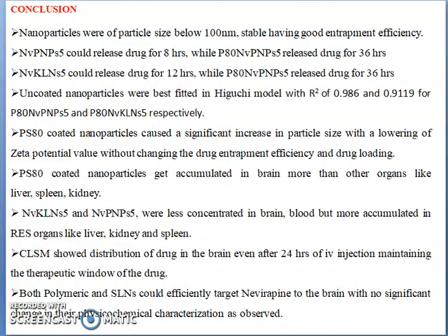So what we can conclude from here is that nanoparticles are very significant in delivering the drug to the brain when surface modified. In our case, polysorbate 80 is used as the surface modification technique. It also extended the drug release up to 36 hours in the blood, which is essential to reach the targeted site. With long-term circulation to reach the targeted site, the amount of drug release will also be more. Here we also found that the drug released in the brain is within the therapeutic window, which is very significant in treating the disease HIV encephalopathy.